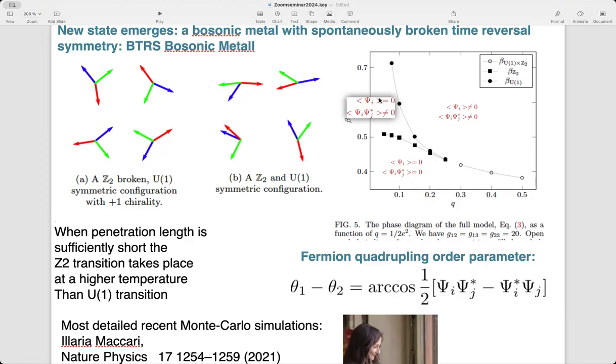But what was most interesting for us is that for that system, at significantly high gauge field coupling, there is a new phase, which is not superconducting. So basically, if one thinks in terms of the gaps, one has phase disordered gaps. One should be careful when talking about disorder in gap fields, because it's a local gauge theory. If I am careful with the formulation, a system is non-superconducting, phase disordered, the phases of the gaps are disordered, or complex fields equivalently, but there is order in the relative phases of the gap.